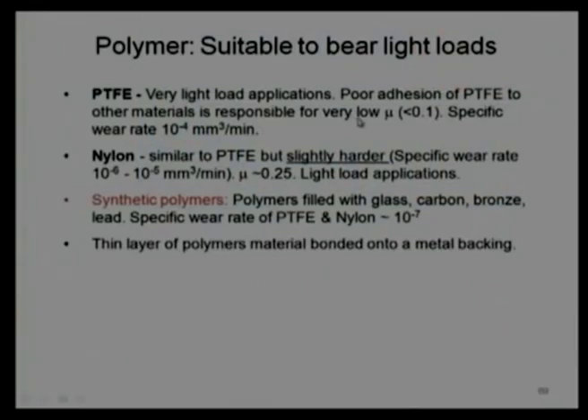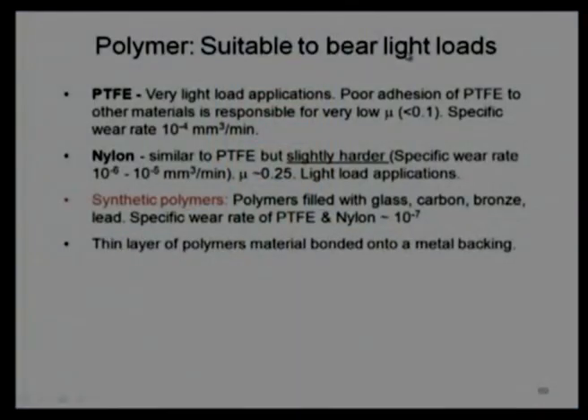Now, one of the major groups of solid lubricants is polymers. We say that polymers are suitable to bear light loads. If you apply a load of high magnitude, they have a coefficient of friction, but we know the coefficient of friction multiplied by normal load will give the friction force, and if the friction force is very high, the rate of heat generation will be high. The rate of heat generation is high and they have poor dissipation. Their thermal conductivity is very low, so they will not be able to dissipate the heat. There will be heat accumulation, which will increase the temperature of these components, and if the temperature increases, then there is a possibility of plastic flow of these polymers, which will cause the loss of the intended function. That is why we say polymers should be used for light load applications only, and sometimes we use the polymers as binding agents, right.